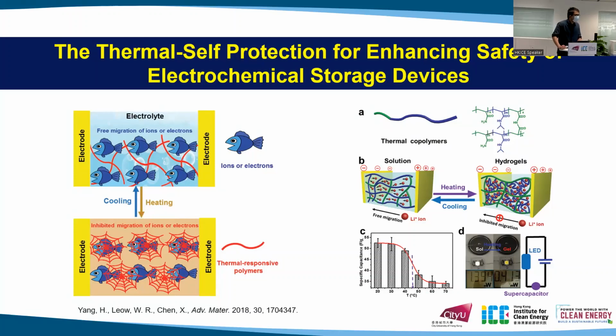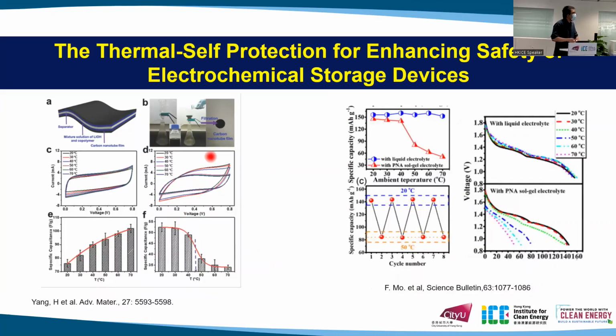And this hydrogel was first applied for the supercapacitor. You can see from here, when the temperature increased, the hydrogel shrinks and squeezes the electrolyte out from the separator, so the LED light is off. By using this kind of strategy, people tried different methods, which could be formed in different ways. For example, here people use the hydrogel to form a thin film as a separator for the supercapacitor. And for this work, people add the thermosensitive hydrogel polymer into the electrolyte.